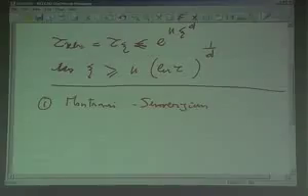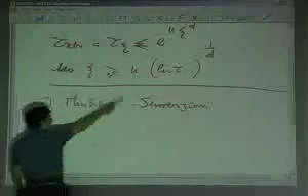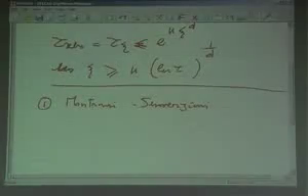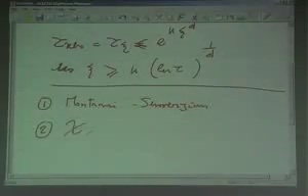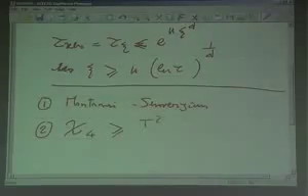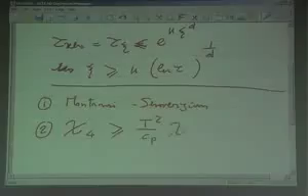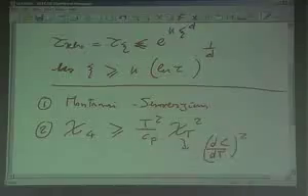In that case, you really get this inequality, exactly like this, with 1 over d, and the length here is the point-to-set length that I discussed before. Another way to get a relation between time and length is exactly what Ludovic discussed. I don't know if you remember, he discussed a relationship between chi4 and chi of t. He said chi4 should be equal or larger than T squared divided by Cp, times chi_T squared, where chi_T is the correlation function derivative with respect to the temperature.